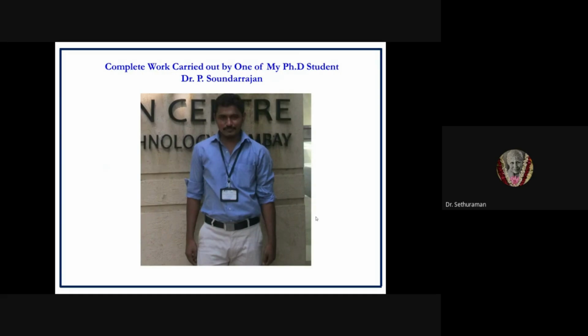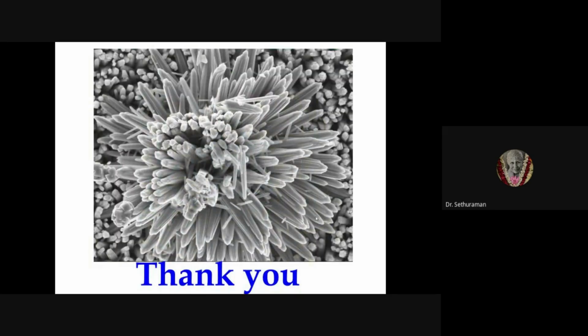Due to time, I will start here. All the structures are prepared on the surface of the glass substrate. We are not using any sophisticated vacuum technique for the preparation of nanorods. We have used only simple solution techniques. On the surface of just a glass substrate, it is very difficult to grow nanorods. We used a seed layer concept, and then successfully prepared nanorod assemblies on the surface of the seed layer.